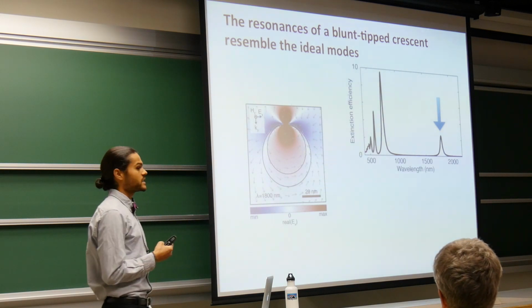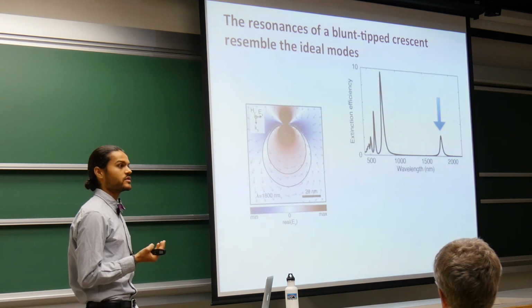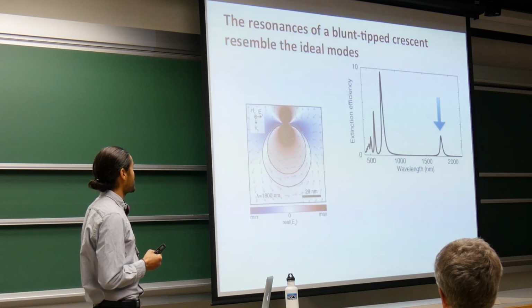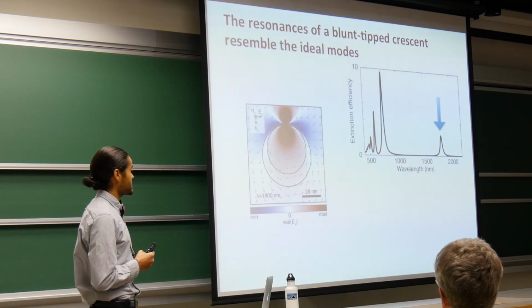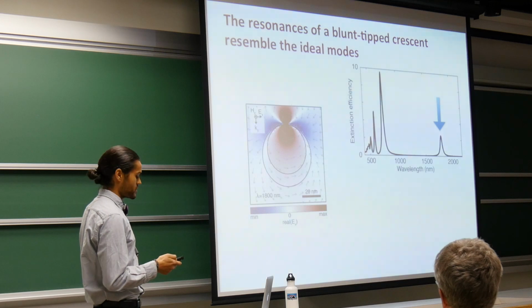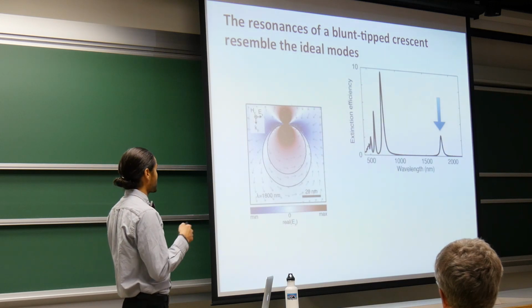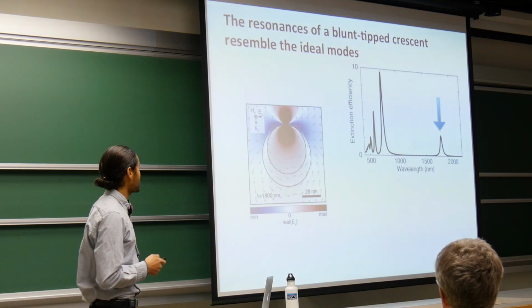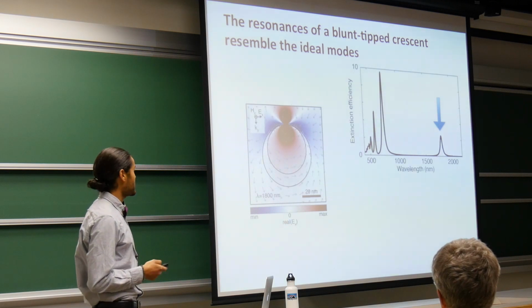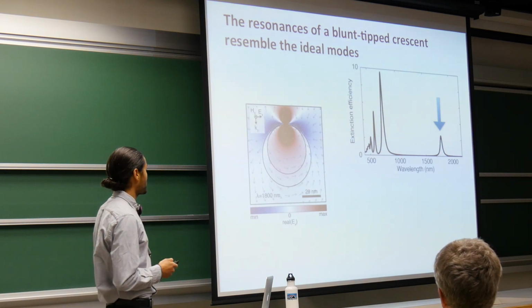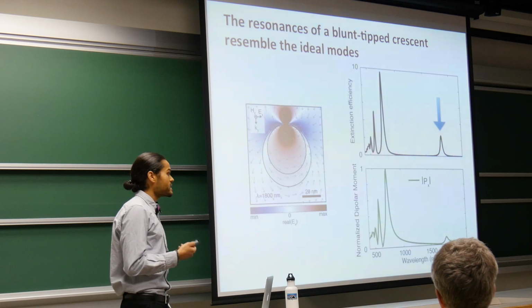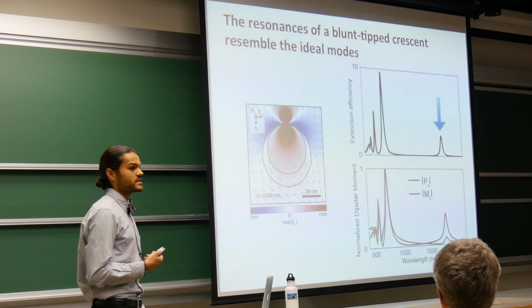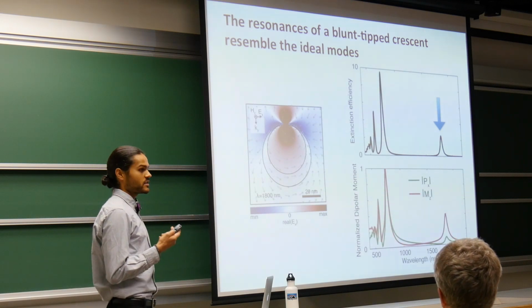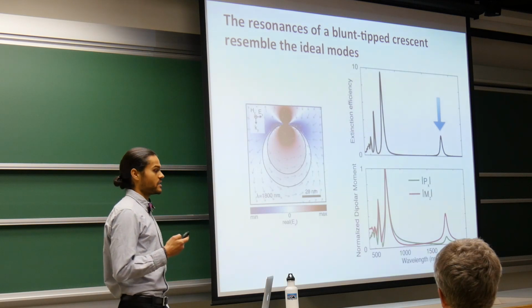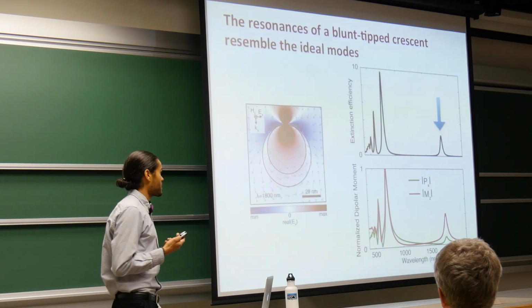Of course, the field intensity at the tips of the structure are reduced because these singular points have been rounded out, but in essence, the character of the mode is preserved. Again, we see the dipolar nature as well as the circulating displacement fields indicating a magnetic dipolar moment. We can more quantitatively describe the resonances of this structure by decomposing the fields scattered by this crescent into their dipolar electric and magnetic contributions.